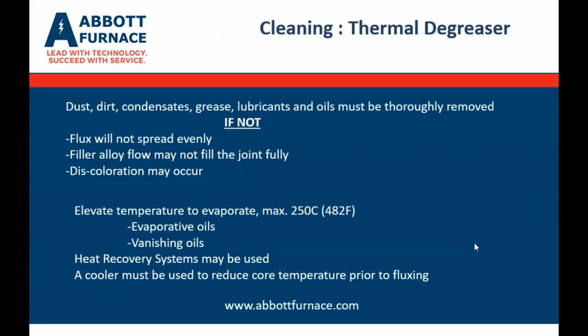Then you have your cooler that's used to reduce the core temperature prior to fluxing. So when the parts come out of the thermal degreaser, they're quite hot. We simply have to cool it down prior to hitting it with flux or water, creating steam.